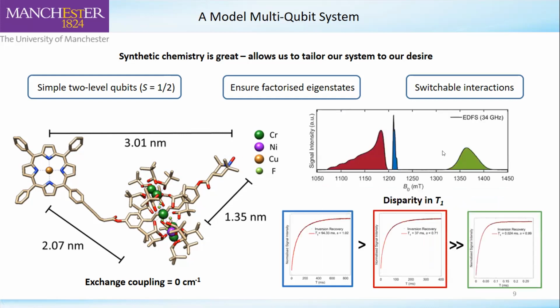At Q-band, if we look at the echo-detected field-swept spectrum, you can see that the spins are completely spectrally addressable. They're completely separated. So we have in red here our copper signal, we have the blue as our nitroxide, and then at quite a low g value is our chromium-7 nickel ring. And in terms of switchable interactions, what we have is a really high disparity in T1, or the longitudinal relaxation of the spins. The T1 for the nitroxide, and this is at 3 Kelvin, relaxes the slowest, followed by the copper, and followed by the very, very quick longitudinal relaxation of the chromium-7 nickel ring.